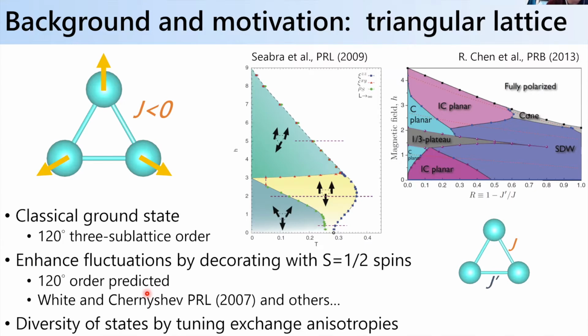But then you can also think of other kinds of complexity you can introduce into the magnetic subsystem by breaking the equivalence of these 3 different exchange pathways, right? So you could go to an anisotropic triangular lattice where you have, for instance, one exchange pathway J, and then 2 equivalent exchange pathways J prime, right? And in this anisotropic triangular lattice, you can end up with non-collinear spin textures, as well as quite a rich magnetic phase diagram, as shown here, in this nice work by Chen.